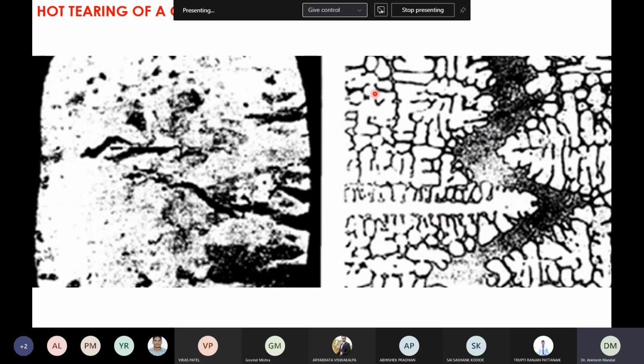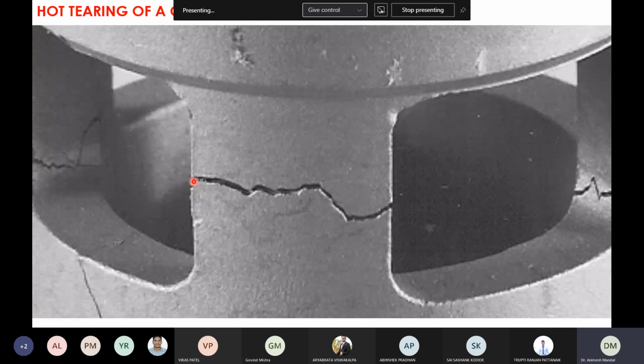This is how it will show up. If you go into the details of the microstructure, you can see intergranular cracks occurring, which will appear as hot cracks on your surface. Like if you see, you can see this component has cracked. It's completely cracked. You can see it's all over the sample, at identical locations. This could be due to poor design of the mold itself, or it could be due to an improper alloy composition. You can see hot cracks everywhere.